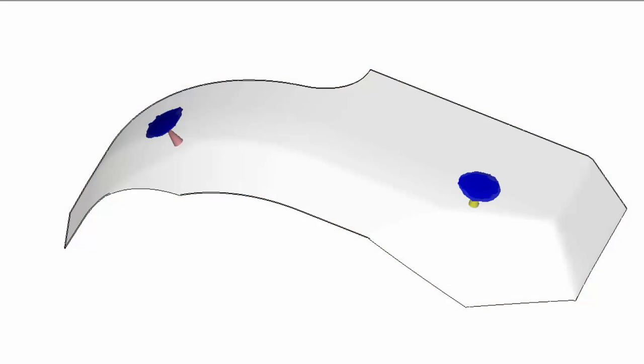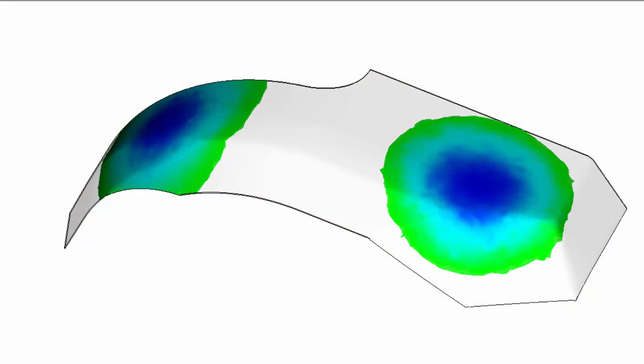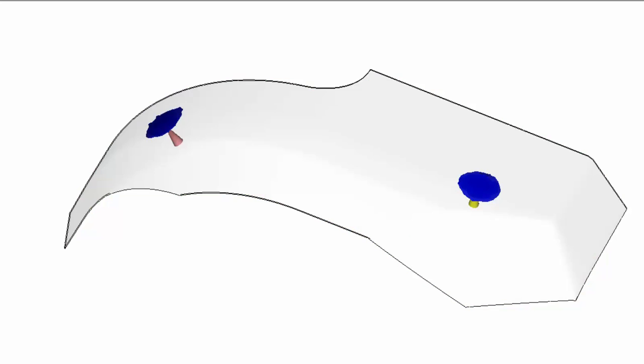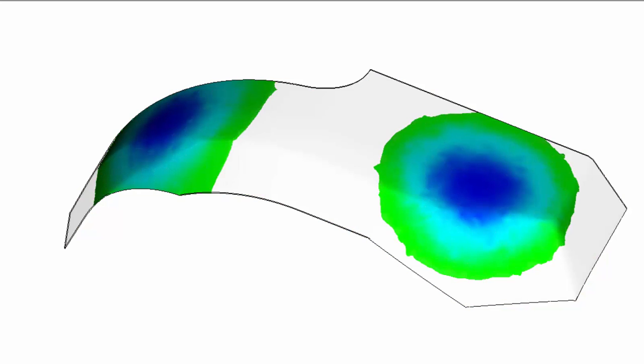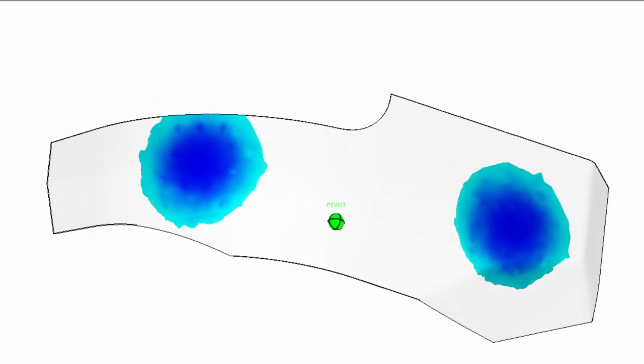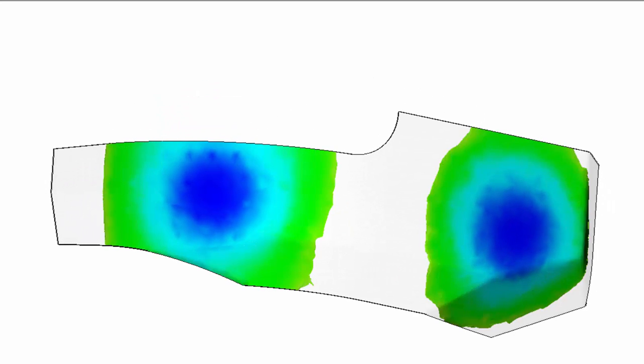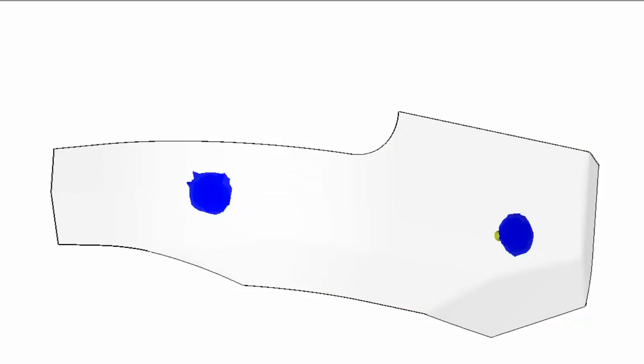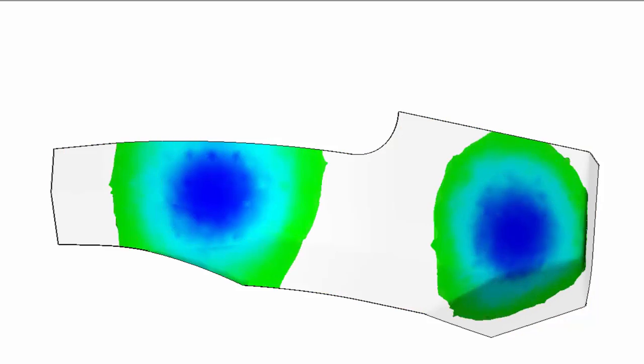In reality, material properties are not constant, the material is not strain-free, and fiber orientations are not perfectly random. In fact, these quantities can vary widely depending on the manufacturing method, such as gate locations. The impact on the structural analysis is as follows.